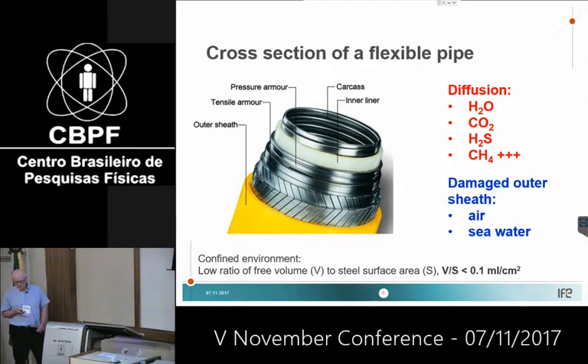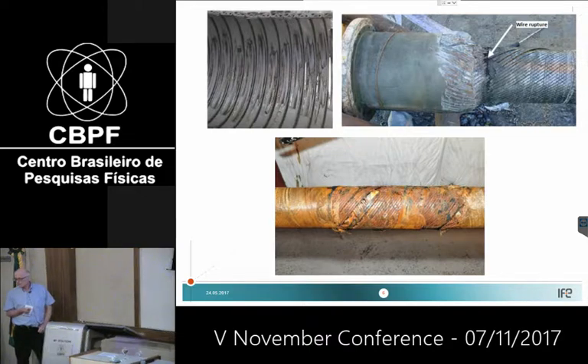And the situation becomes much more complicated, at least more complicated, if you have a damage in this outer sheet, that is either in air, in a splash zone, or in a sea. And then you get air with oxygen into the system, you get seawater into the system, you can have several damages, so you get some kind of a circulation in this annulus. And all that makes it very difficult to both understand and predict what is actually going on. And these are failure cases. Here you have got corrosion on the wires. Here you have got cracking on the wires. And this is what we fear. And this is what we have to predict. And we have to find methods to avoid it.